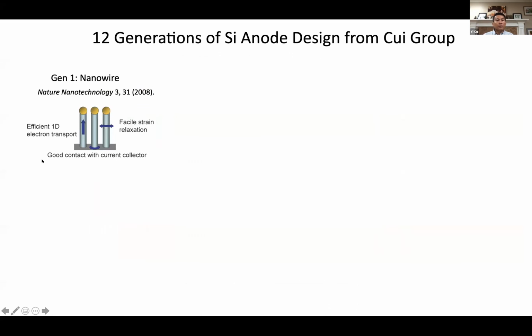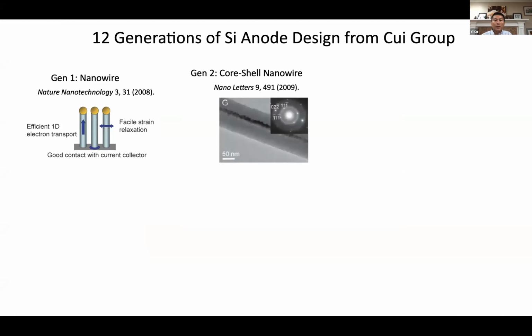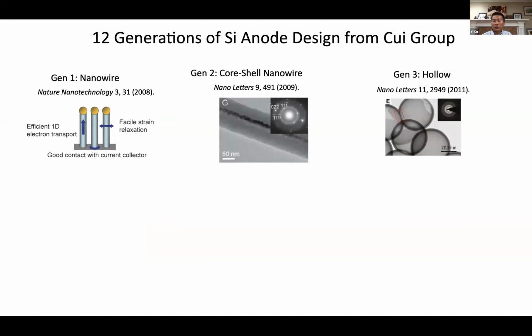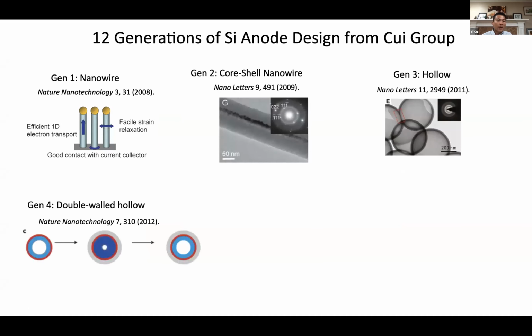So with this, we have been through more than a decade-long of material design, starting from the wires, using the core shell to enhance the stability, and hollow structure to relax the strain even better. And to build a stable interface, we need to avoid the volume expansion towards outside. So we designed this double wall hollow structure. The silicon in there expands towards inside instead of outside. The red color coating with the wall forces the volume expansion towards inside and forms the stable interface.